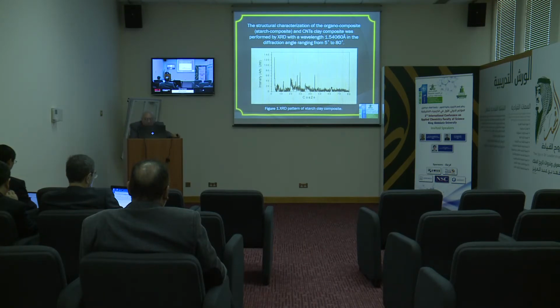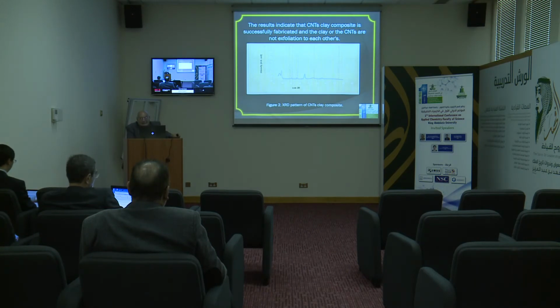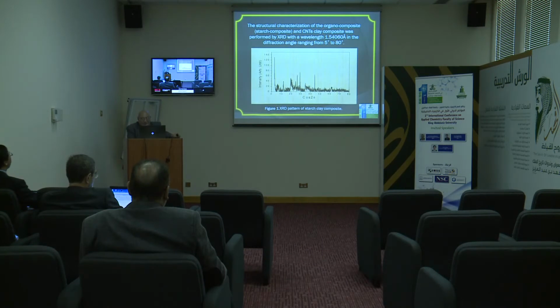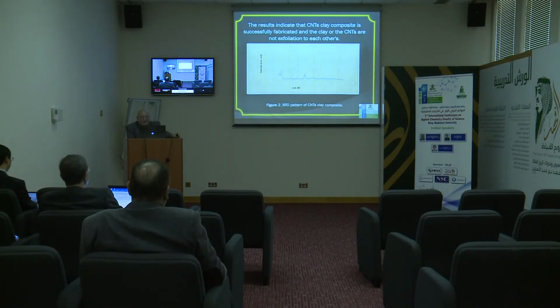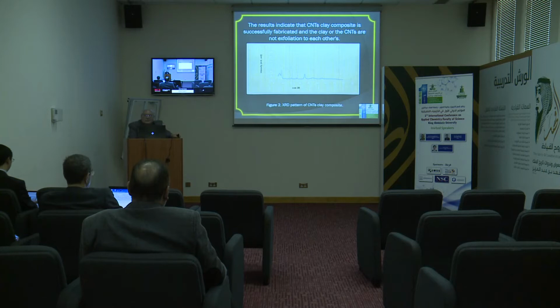Here is the figure of the XRD pattern of starch clay composite. The results indicate that carbon nanotubes clay composite is successfully fabricated, and the clay and the carbon nanotubes are not exfoliated to each other. Here is the XRD pattern of carbon nanotubes clay composite.